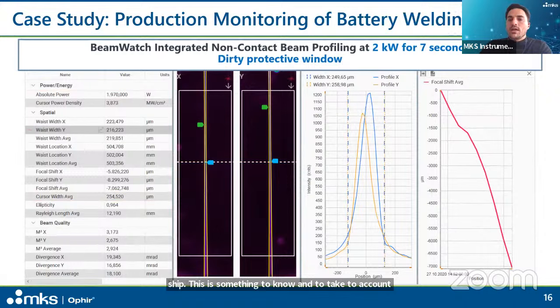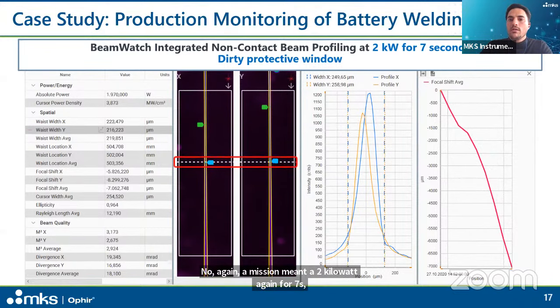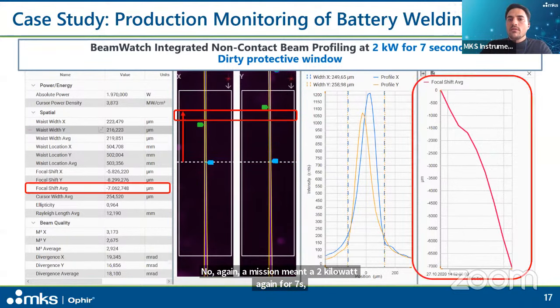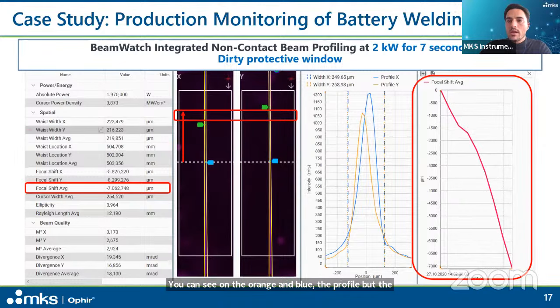Now, again, a measurement at 2 kilowatts, again for 7 seconds, but in this case with a dirty protective window on the optic. And here you can see that we have a focus shift of 7 millimeters, as well as significant astigmatism. You can see on the orange and blue beam profiles that the focus is not at the same position for X and Y.